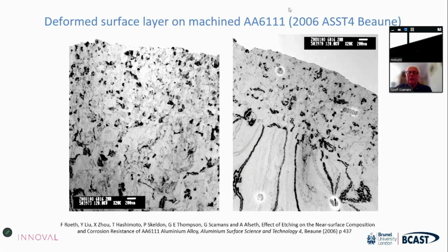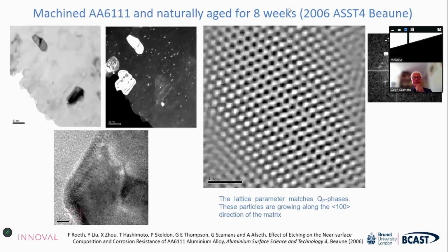About this time, a PhD student in the department, Frederick Roth, also did some really nice work on machined 6111 surfaces, showing beautiful deformed surface layers of ultra fine grains. And he was also able to show that not only do you get preferential manganese precipitation, manganese dispersed precipitation, you also get preferential precipitation of aging precipitates. So he looked after, having had a machine surface for about 8 weeks, he then was able to do some ultramicrotomy and TEM, was able to show rapid development of aging precipitates on these surfaces, and did a very nice microscopy to show what phases these are.